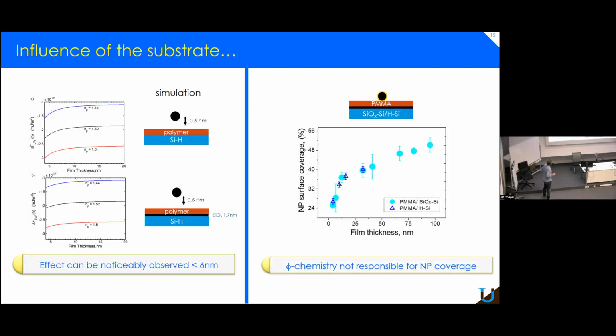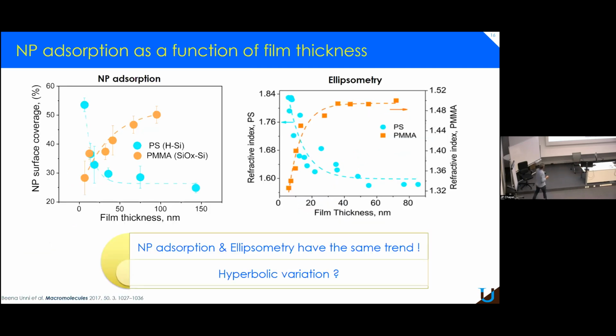Here is just the same experiment that we saw before. We just made the PMMA films on silicon wafer with or without the silicon dioxide layer, and actually the trend is the same. Okay, so the physical chemistry of the substrate is not responsible for the nanoparticle coverage. So here, those are the two curves that we did obtain at the end: the NP adsorption that you just saw, and the ellipsometry measurement that we did again, and you see that the two variations are really similar. Obviously, this is an ellipsometry result; it's model dependent, but this experiment is not model dependent. But I agree that here what we see is only the adsorption, and we saw before that this adsorption is related to the variation of the refractive index of the film and then to the density inside.